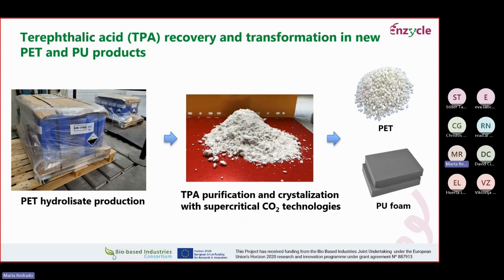We tested different protocols at lab scale, but for pilot scale, we employed supercritical CO2 technologies for the purification and crystallization of this compound. And we have successfully produced kilos of this material, which are transferred to companies that are testing their suitability for the development of new PET materials and polyurethane foam.